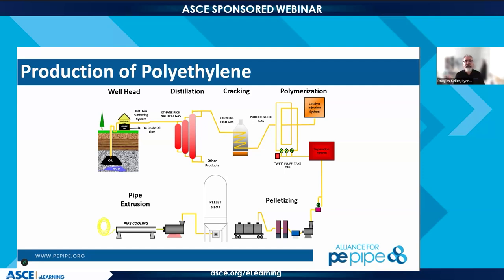That ethylene is then introduced into our polymerization step. In the polymerization step, we use a catalyst in combination with heat and pressure. We open up that double bond and we start to link those ethylene chain or monomer units together to create polyethylene. So polyethylene is many little ethylene units. You can think of it as a chain link where each link is an ethylene unit. We're making varied molecular weights depending on the application that we're going after. That comes out of the reactor. We separate it off from the reactants that weren't reacted and it goes into our pelletizing step.